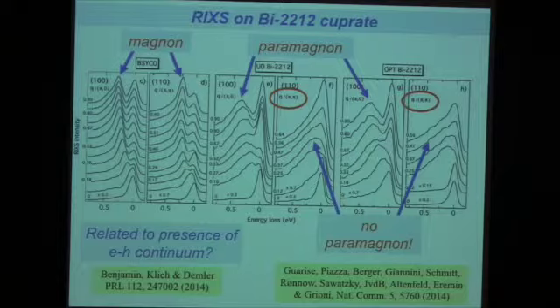But now the kind of devilish thing is that for the undoped system, we see clearly magnons. And now they gradually change, they become wider, they change somewhat in energy, but nothing radical happens upon doping. While you would argue, if it's purely electron-hole excitations that kick in if you dope the system, why should this electron-hole excitation continuum look like a magnon for the undoped system? Why should that be the same? Of course, there are calculations, but there's no a priori argument. So that's what I would say. That's a very unfortunate coincidence or complicating factor, if it is that way.